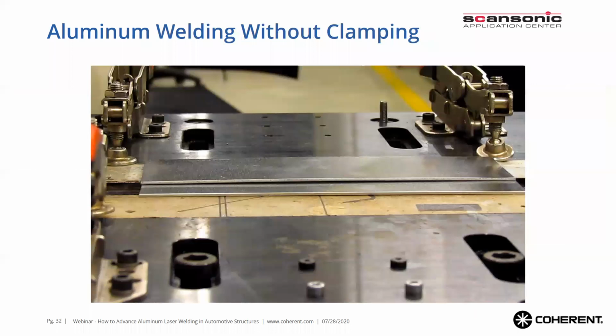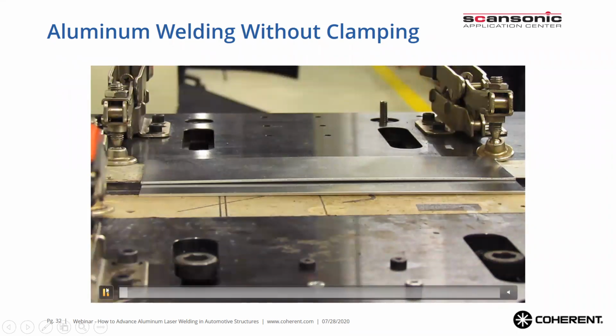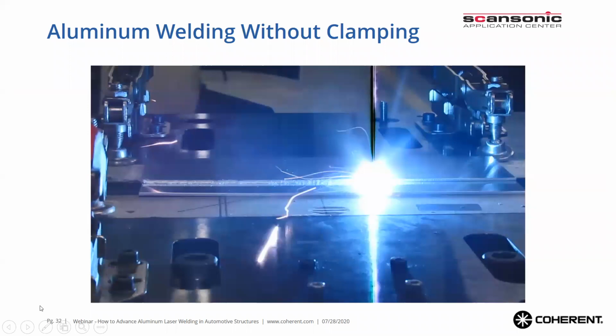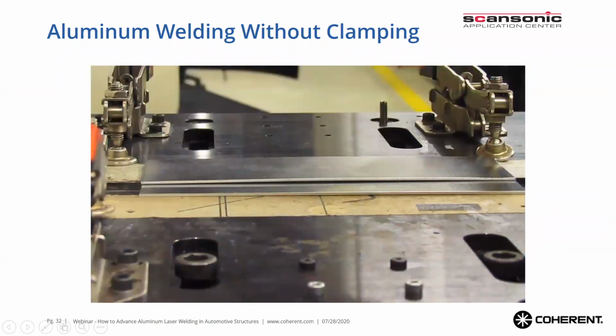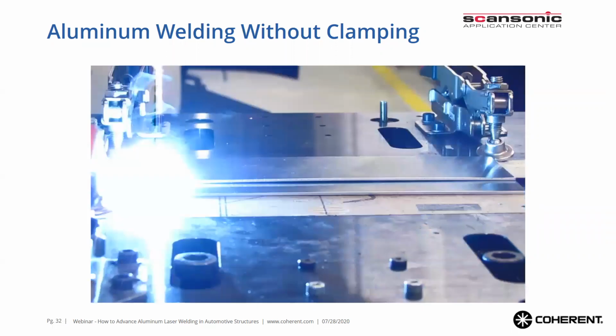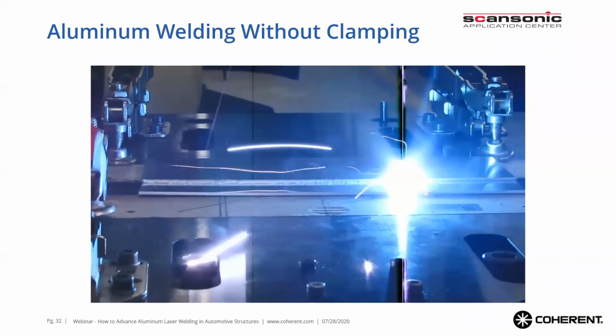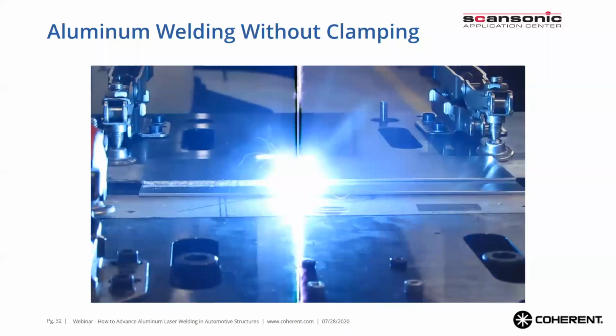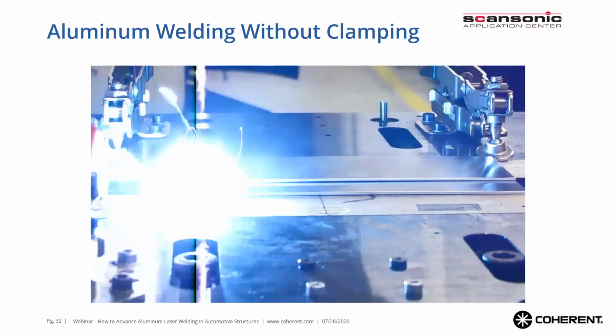Now, this is very interesting in that you're looking at the same fillet weld, but here with no clamps applied. So the material essentially is just laid on top of each other like this, and you can visibly see that there's a huge gap in the center. And what's interesting is when the laser is turned on, it is automatically adjusted, and you can see that this part is warping and moving, but the beam and the laser parameters are automatically adjusted to get a successful weld. So very interesting.